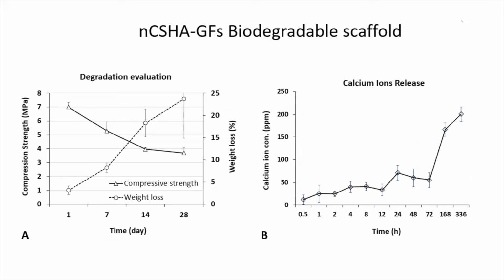In addition, we hope this material is degradable, so that the degraded space could be replaced by regenerative tissue. Thus, we tested the biodegradable ability of our material. From this result, it can be seen that the scaffold will be significantly degraded on the 7th day. This is also obviously related to the calcium ion release profile. After the 7th day, there will be a large amount of release.